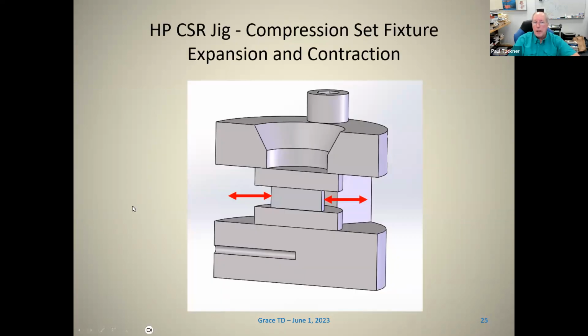One thing about a CSR jig is that it's really a compression set fixture if you want to use it for that. When you compress the specimen, it has to expand radially to keep its same volume. When heated to elevated temperature, because it's constrained axially, it also expands radially. Then when you cool it back down, normally it contracts radially to its equilibrium position.